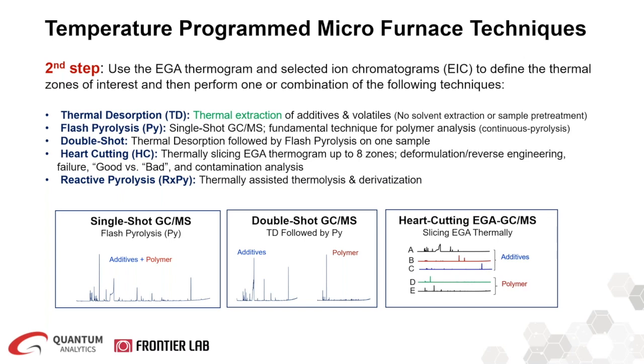So first, all the additives, volatiles, and lighter components are thermally extracted from the mixture, and you obtain a thermal desorption chromatogram. And then the flash pyrolysis is performed to analyze the heavier and polymeric compounds from the pyrogram. You could also perform heart cutting, which is the multi-step thermal desorption and pyrolysis. So in this case, the EGA thermogram is sliced into multiple temperature zones depending on the thermal zones obtained from the EGA.